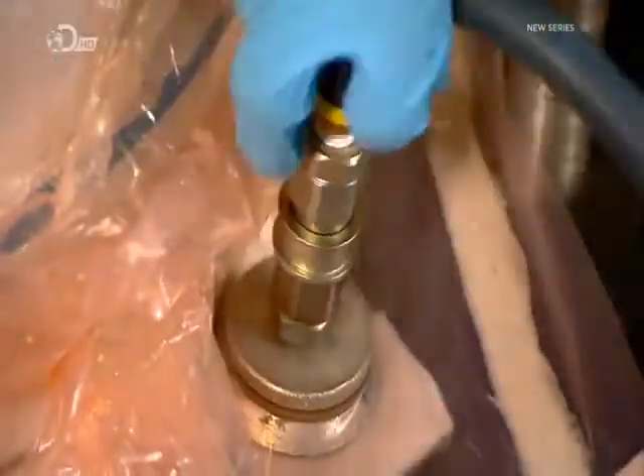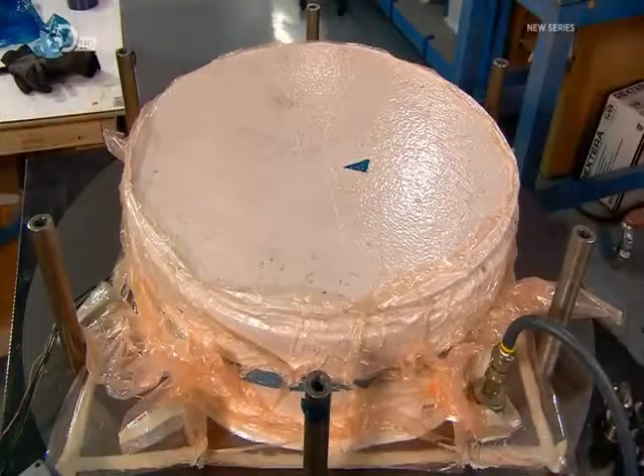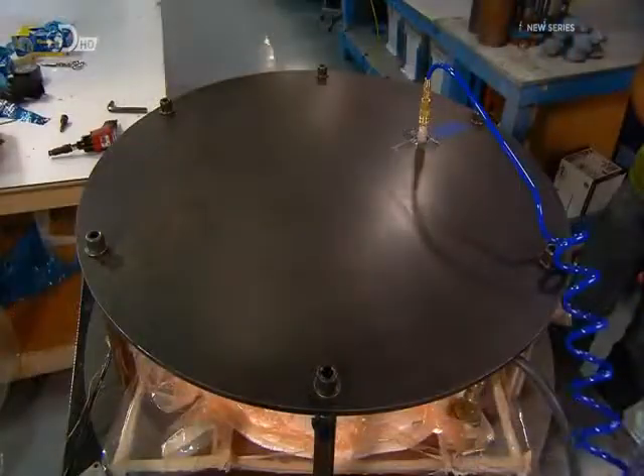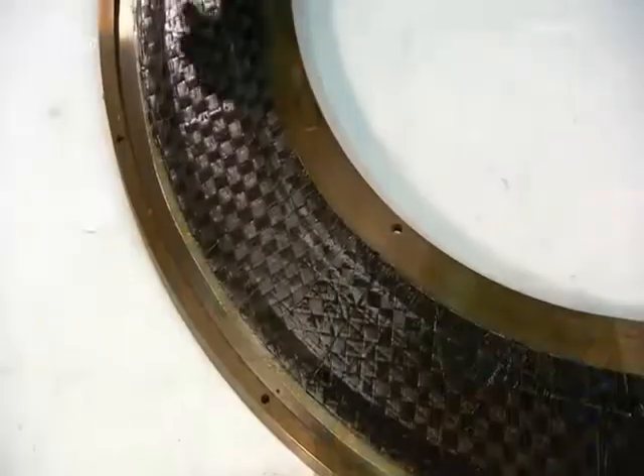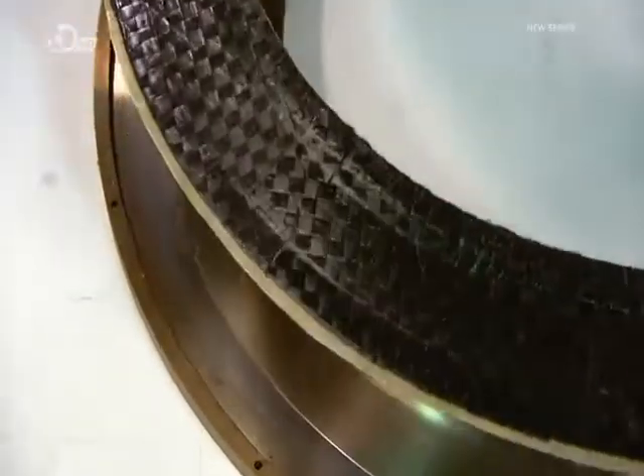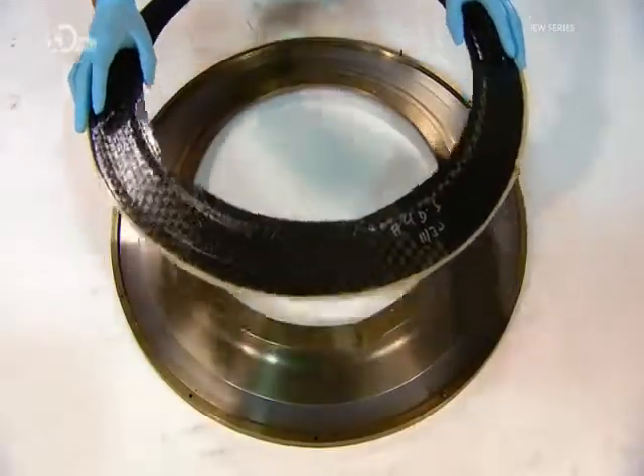He wraps a heater pad and a plastic vacuum bag around the stack and activates the vacuum. It sucks out the air to pull the melting carbon fibre to the shape of the moulds. He adds an air bladder and a metal plate. This applies more pressure as the carbon fibre solidifies into a sidewall shape.